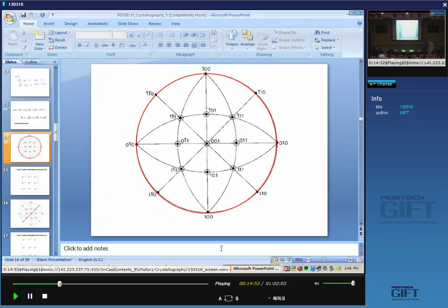And what I'm going to do now is to plot the reciprocal lattice section, which is normal to 001. Okay, so if I'm looking at the plane which is normal to 0, 0, 1, which is pointing out of the board, then all the poles lying on this great circle, which are at 90 degrees to the 0, 0, 1 direction, will appear on my reciprocal lattice vector zone. So how do I do this?